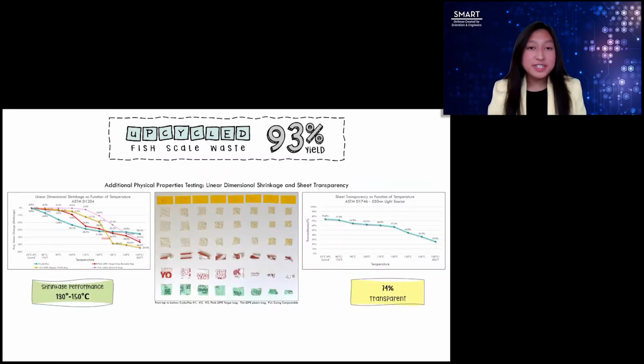Cycloplast also had higher shrinkage performance from 130 to 150 degrees Celsius, whereas LDPE melted and deformed. This is because cycloplast is primarily protein, which does not melt, shrink, or deform at these temperatures, especially in the absence of water due to thermal dehydration. And as temperatures increased, transparency also decreased from 74 to 25.8%.